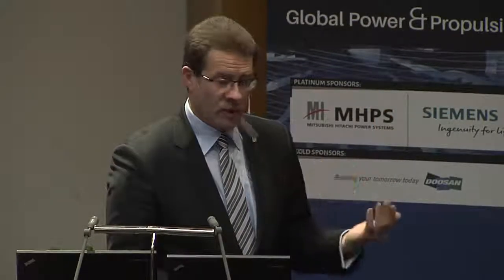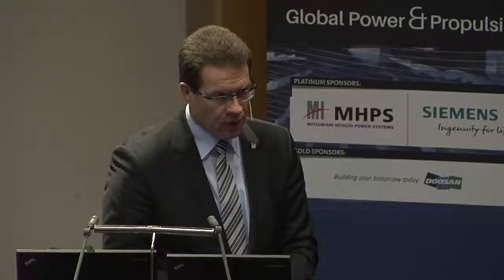So this is extremely important. This is what I say. When using additive manufacturing, you're also building the material, and the material's properties are important for the properties of the component. Yes, there is a lot more work to be done. We have seen applications, for example, aerospace applications, where additive manufacturing is being used for repair of blisk structures, where fatigue is a problem rather than creep. We are able to rebuild the airfoil within the spec of the properties that are required for a new part, which is coming out of a forged billet and then machined down. So it depends on the part, it depends on the component, and it depends on the material. But you are certainly right.